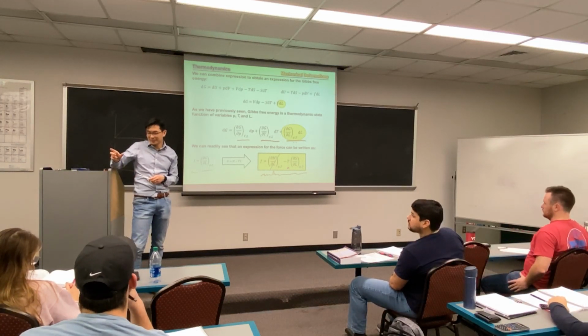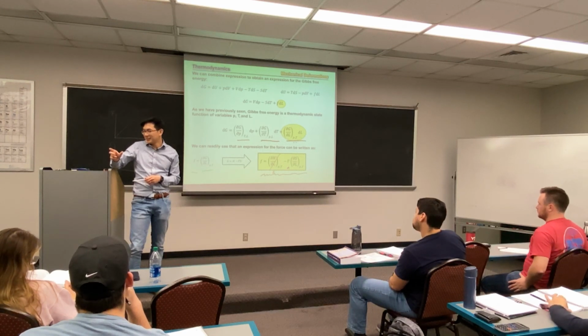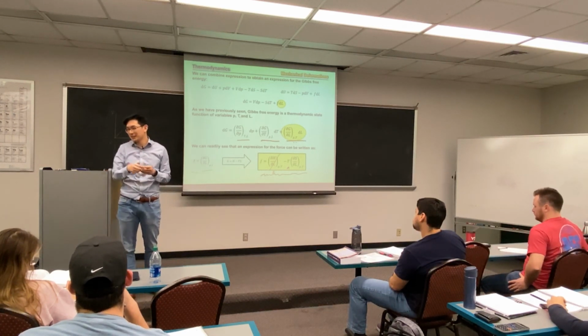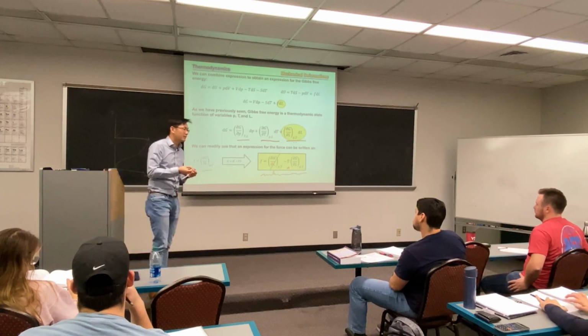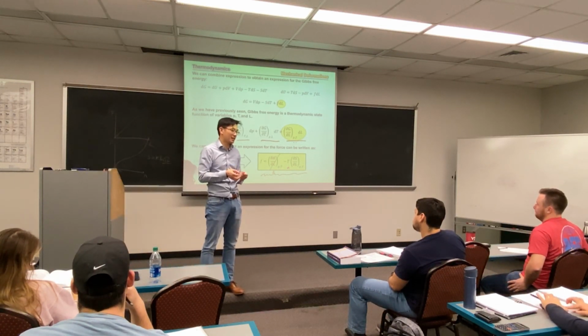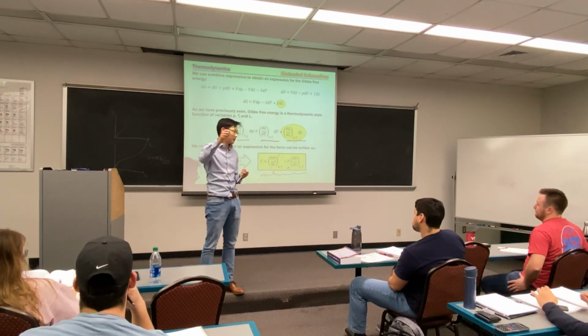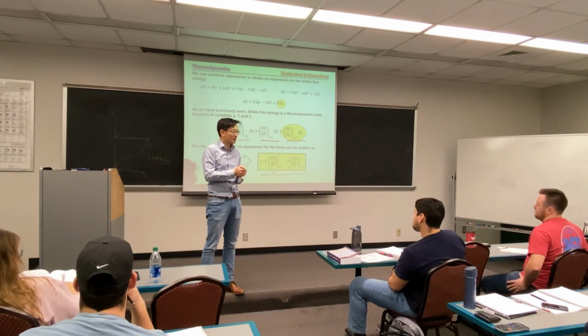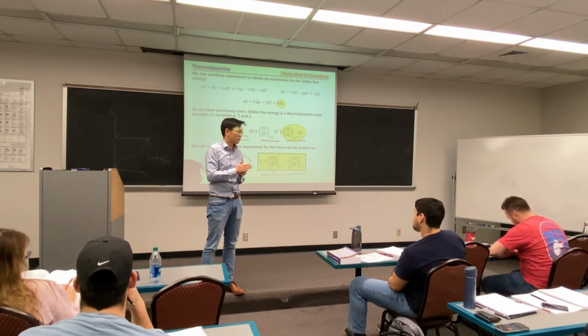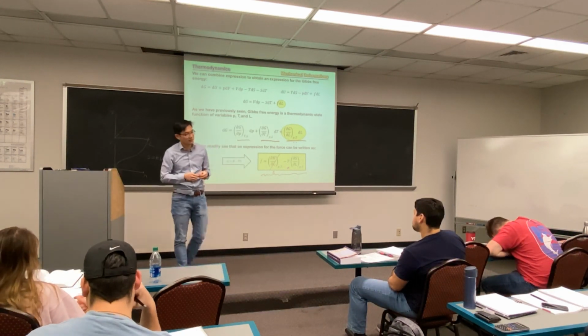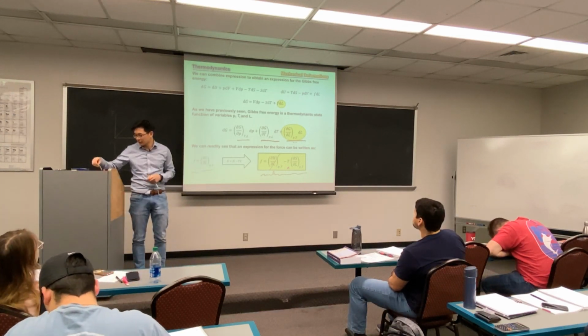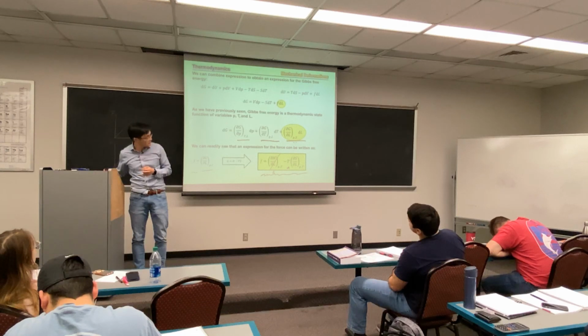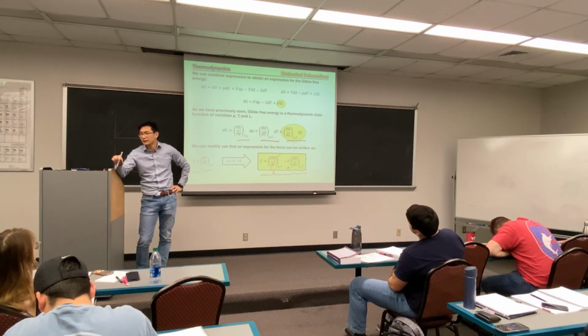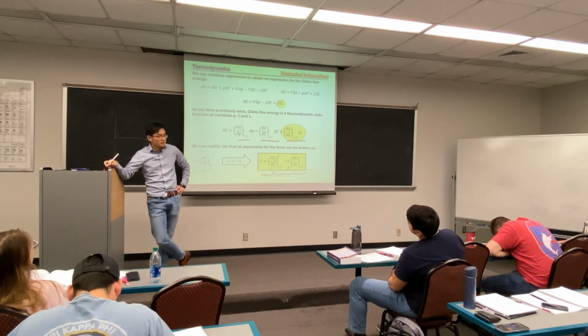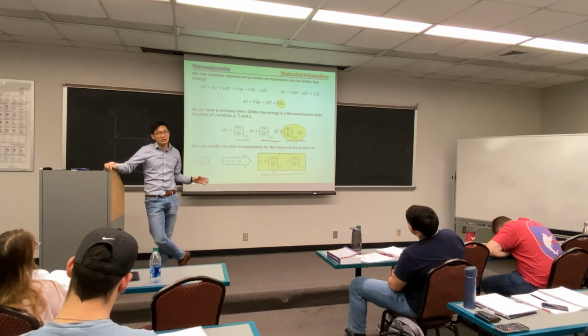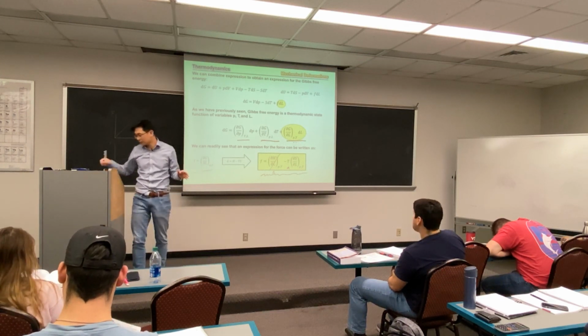And with this, you can use the rubber elasticity theory to predict the modulus will be on the order of megapascal. If you cross-link them at 10 times lower density, which means instead of putting so many cross-link points along the backbone, the modulus will drop proportionally. In other words, using the rubber elasticity theory, we can understand how modulus changes versus different degrees of cross-linking. We will talk more in detail, but I hope this lecture is trying to get across an important message.